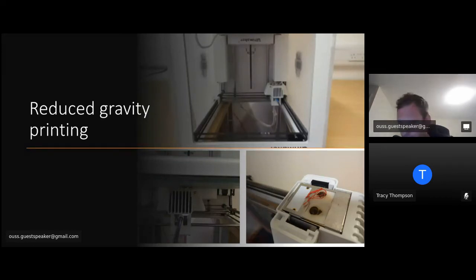As you can see on the bottom right there, it didn't quite come out well the first time I did it. The extruded material came out onto the extruder tip, and it just made a big mess. So the first thing I realized was that getting a good adhesion to the bed was really important. And the purpose of this was to show whether there is any difference between printing at 1G or any other type of gravity, reduced gravity, -1G or whatever. And there was no other data I could find anywhere. So I went ahead and decided to just try and print something upside down.